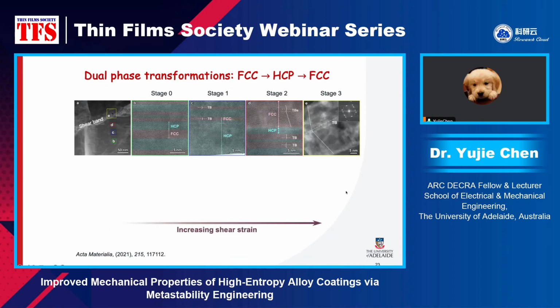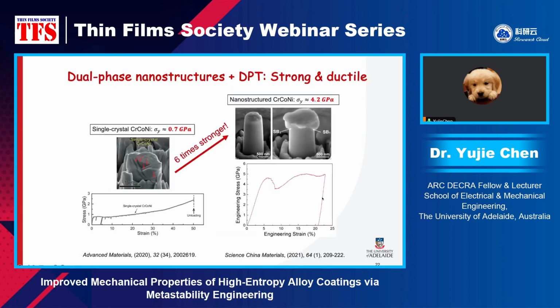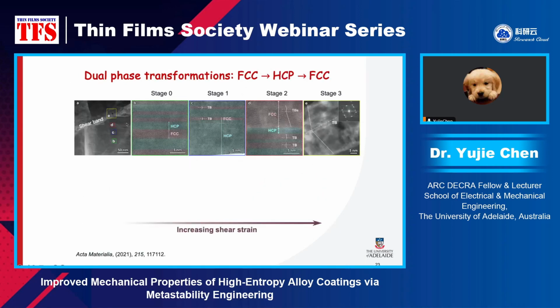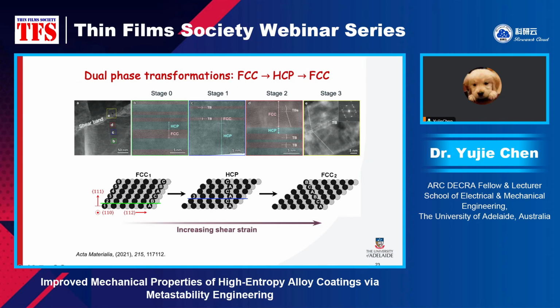We found this alloy shows a very interesting deformation mechanism. That's the most important thing of this study. It's dual phase transformation. Basically, what we have done is, after this micropillar compression, we prepared a TEM sample of the deformed pillar. And in that pillar, we see this shear band. And then we analyze the phase structure at different strain levels. If you're close to a shear band, the region has experienced larger shear strain. So we check the phase structure in these four regions, and we found that the material has experienced a two-step phase transformation from FCC to HCP and then back to FCC.